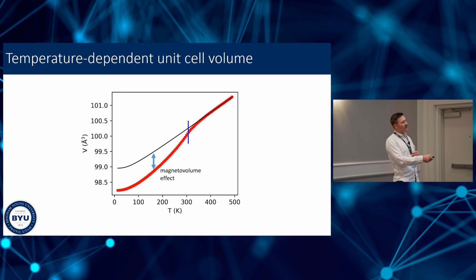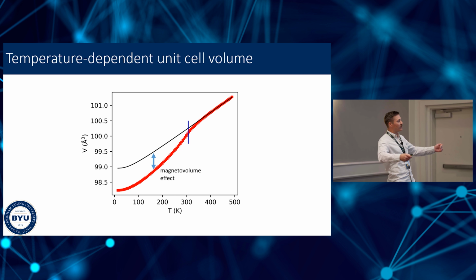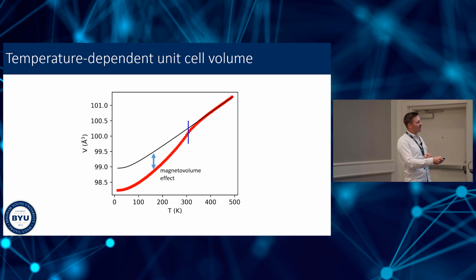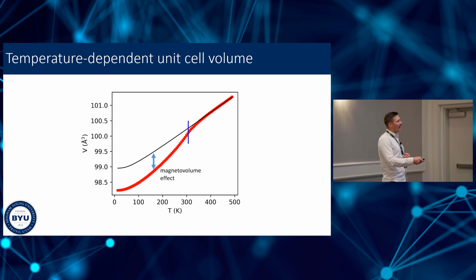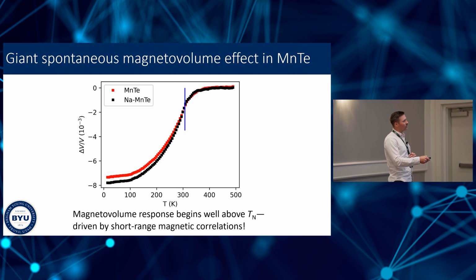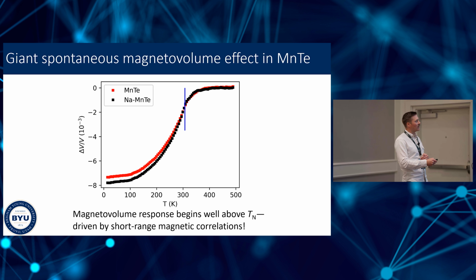You may notice it starts above the Néel temperature, right? The blue line here, this is 307 Kelvin. This is where the long-range magnetic correlations kick in. And yet, the deviation from the non-magnetic expectation begins well above that temperature. Okay, we can plot the fractional volume change, delta V over V, for both a pure compound and a sodium-doped compound, which I won't talk too much about today. But again, this is highlighting that this anomalous contraction of the volume begins well above the long-range Néel temperature.